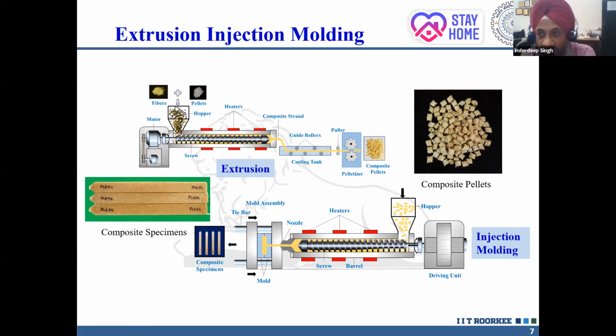Now, this is also related to CNC programming, because here also there is a controller and there are codes in the injection molding machine that we have to program so that we are able to properly select the mold opening time, mold closing time. We have to see how much temperature we have to set, and the barrel is a long barrel, so we have to establish a temperature gradient in this barrel. So at different sections we have to control the temperature, and we have to define a temperature profile through which these pellets will be melt blended once again into the composite specimen.